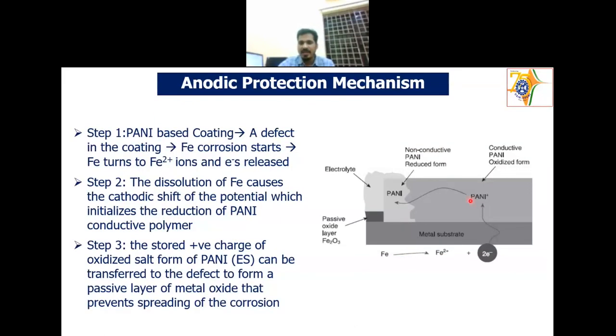Actually, when you are adding Pani in the coating, there are three steps happening during the anodic protection mechanism. First, step one, you have the coating. Suppose the coating is defect free now. But now when a defect comes in the coating, the electrolyte is entering here. So Fe corrosion starts. When Fe corrosion starts, Fe is giving Fe2+ and 2 electrons. The electrons being released, the dissolution of Fe causes the cathodic shift of the potential, which initializes the reduction of the Pani conducting polymer here.